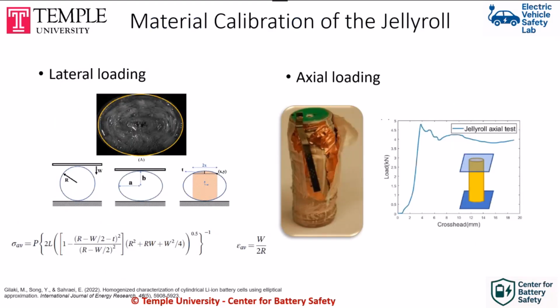If we have cylindrical cells, then we also need to understand the geometry is not as simple as pouch cells. So we have to apply global loads radially and do some analytical calculations, maybe use a virtual work method, and then get the relationship between stress and strain from that type of radial loading. But if we just need to calculate the buckling strength, that's easier because the jelly roll is stable on itself. So we can apply the axial force and get the buckling strength for that.